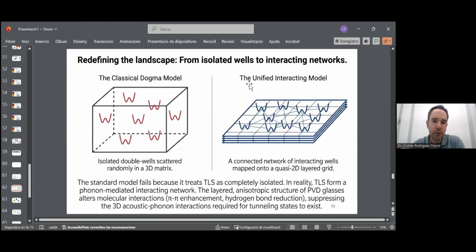So, the conclusion, the argument we said, was that we have some kind of requirement of cooperativity between different TLS, okay, that was removed in the case of the ultrastable glass because of this layering. This layering was somehow acting as a breaking of this cooperation between two-level systems. When we add water into the system, for this degradation, we can recover again this network of TLS, and that's why we change from not having TLS to having TLS.